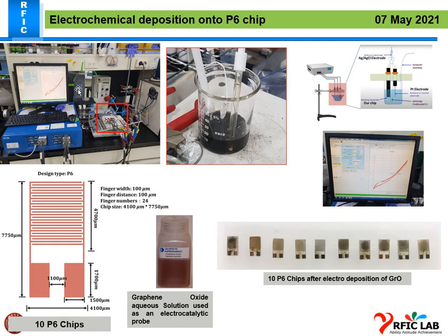So this is the electrochemical deposition system, the place where we use this kind of setup. We have 3 different kinds of electrodes. First is the counter electrode, which is platinum, the second is the working electrode, and the third is the reference electrode, an Ag/AgCl electrode. So the chips I used last week were the 10 P6 chips, and this solution I used as an electrocatalytic probe, and these are the 10 chips that I made with this machine.